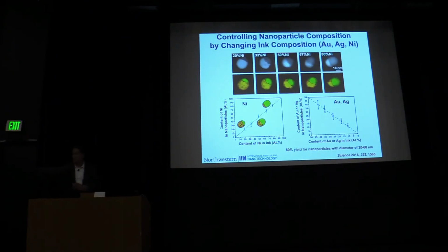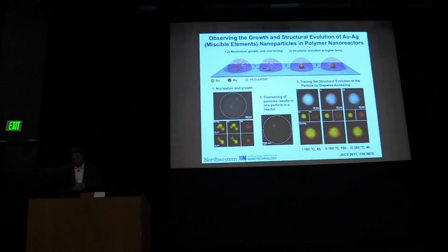There's a linear relationship here, and that's why I keep saying that everything we put in the reactor goes into the particle. That's kind of an interesting consequence here. And you can see we intentionally kept the gold to silver ratio 1-to-1 throughout the different particles that were made. Here's an example of being able to study what goes on, for example, in a reactor with respect to more complex systems. The alloys, how does that silver gold alloy form? Well, we can study that because we can set the reaction up 1-to-1, silver ion to gold ion within the reactor, and then we can map it.